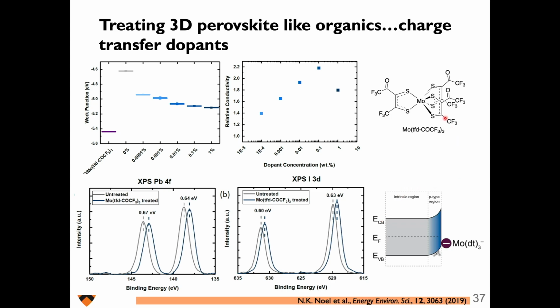This is a well-known one, this Mo(tfd)3 compound, a strong oxidizing agent. What we see is that putting this on the surface does in fact make a much deeper work function, but you can see the conductivity of the system is basically unchanged. And so what has happened with such a system is I'm doping it, but I'm just doping the surface. It's not doing anything to the bulk properties of the perovskite. The XPS shows even the core levels are shifting, not just the work function, but everything is really shifting. So the surface is really getting p-type doped, but it's not infiltrating the bulk. And so it's just a surface doping.